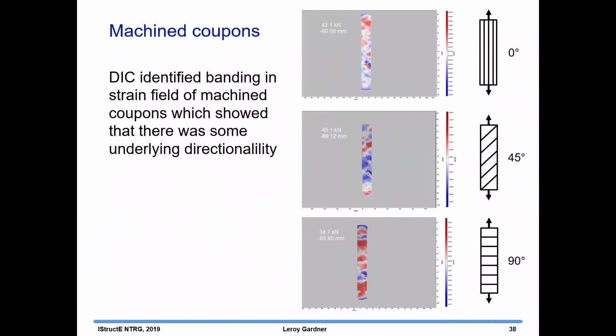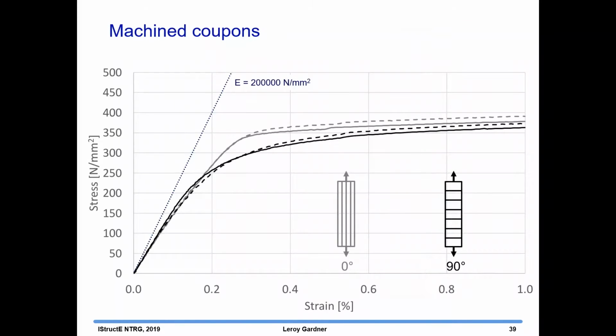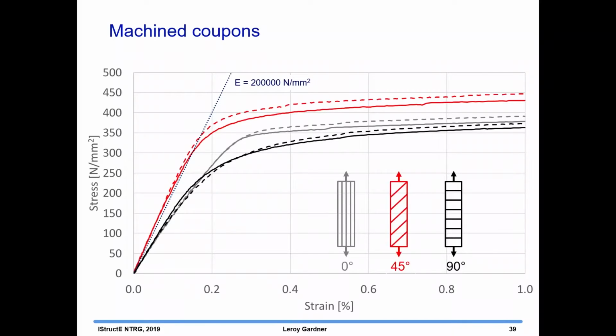So we were able to get strain output, and we did indeed see that you have this banding effect and an underlying directionality to the material properties. And you see some of this in conventionally produced material, but it's more pronounced for 3D printed material. So looking at the stress strain curves, in the 0 and 90 degree directions, for the machined material, we found that the Young's modulus was about 25% lower than conventional stainless steel of this grade, whilst in the 45 degree direction we found that the stiffness was actually slightly higher than the normal 200,000 newtons per millimetre squared.